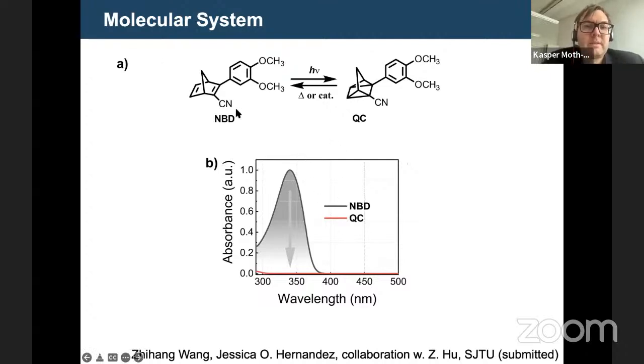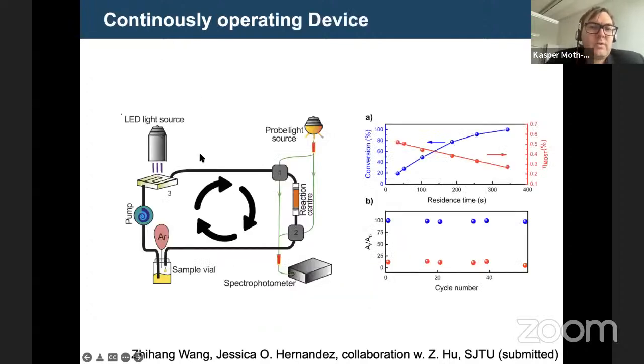Later we worked more with this, and this is a little bit optimized molecule, and showed that we can continue to operate this cycle for many cycles without any degradation. Simply irradiate, store, trigger the heat release, and recover, here for 50 times during a continuous operation.